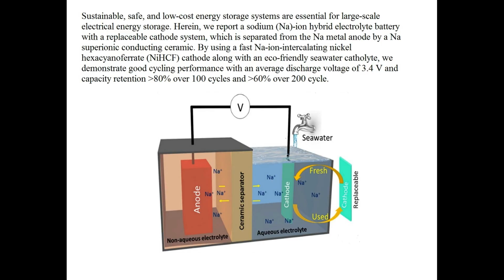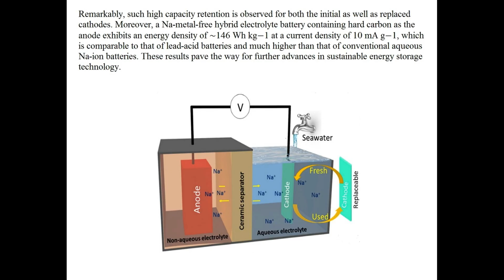By using a fast Na-ion intercalating nickel hexacyanoferrate, NiHCF, cathode along with an eco-friendly seawater catholyte, we demonstrate good cycling performance with an average discharge voltage of 3.4 V and capacity retention of 80% over 100 cycles and 60% over 200 cycles. Remarkably, such high capacity retention is observed for both the initial as well as replaced cathodes.